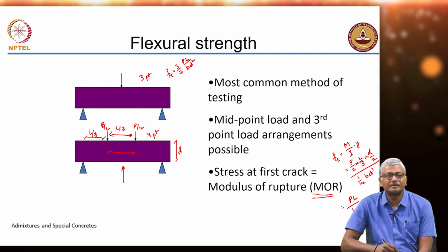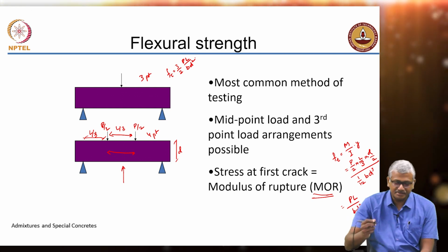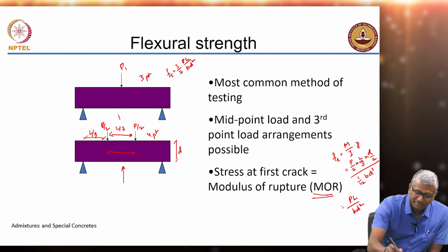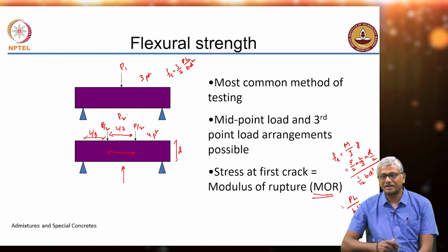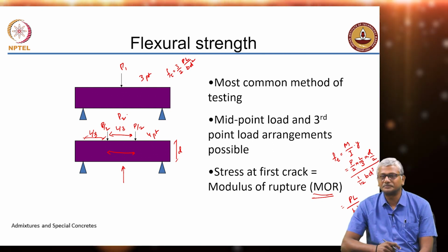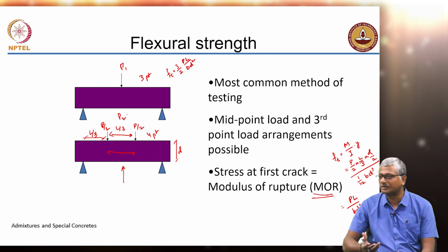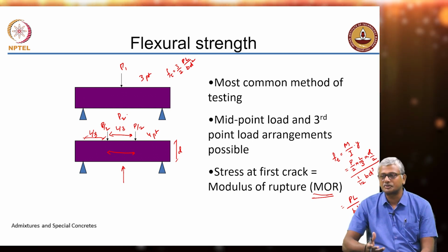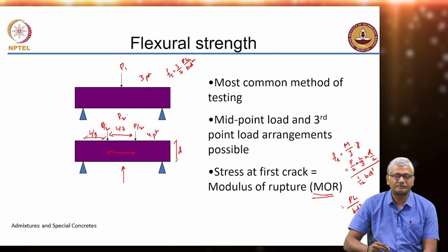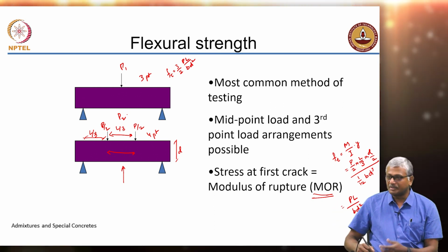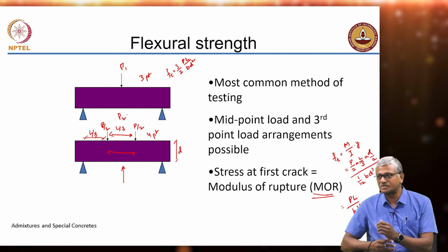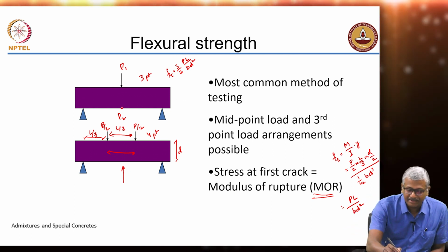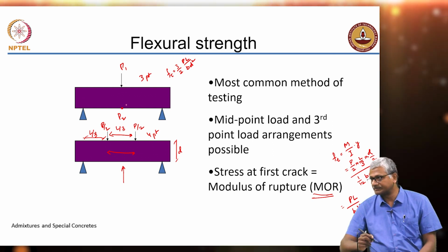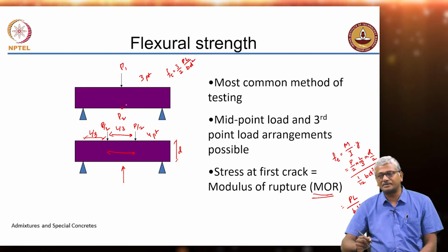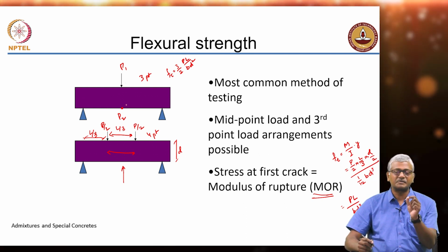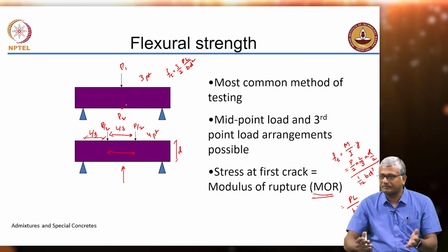Yes, obviously. So, this is P1 and this is P2. You are getting the crack at different loads. Depending on which way you do the test, you will get different loads, and when you do the calculation, you will get approximately a similar value for the modulus of rupture. There may be some differences because of the presence of some shear, because only exactly at the center do you not have any shear. So, if your crack is exactly at the center, then you have an infinitesimally small zone of pure bending, otherwise you will have the effect of shear also.